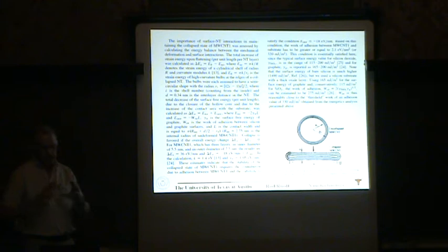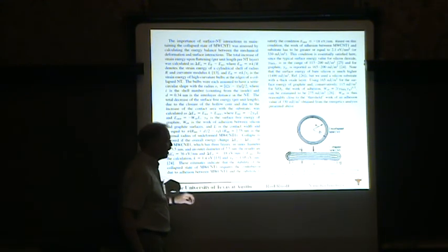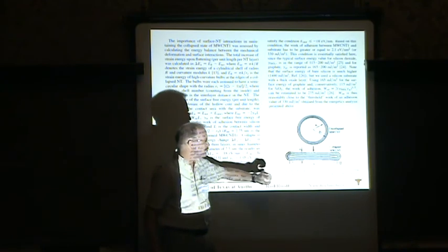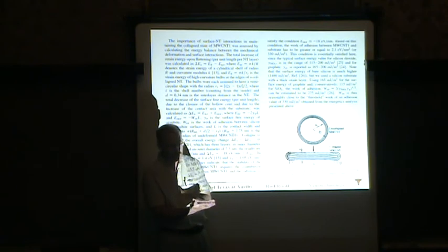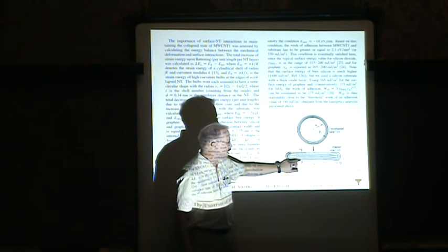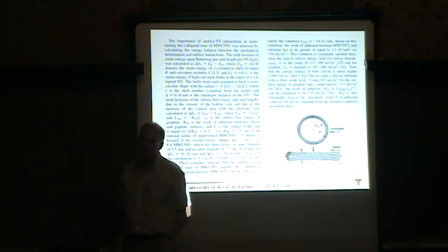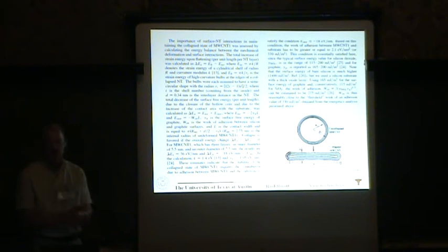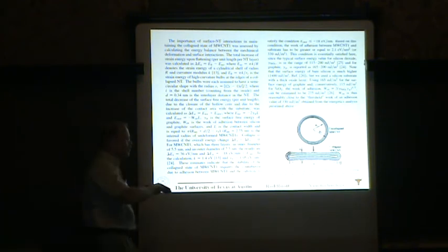You're taking a cylinder and deforming it elastically. And so there's an energy penalty for creating these relatively high radius of curvature bulbs. But there's favorable adhesion occurring here where the innermost cylinder has collapsed onto itself, and then a larger surface of interaction with the substrate, such as silicon dioxide. So the surface energies need to be accounted for. The energy to deform the tube needs to be accounted for.